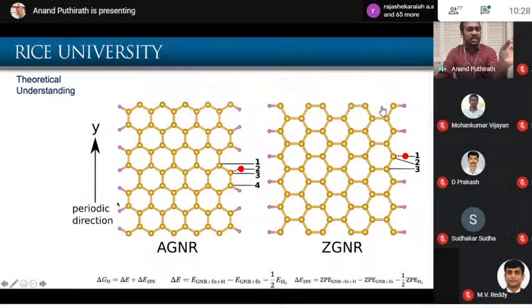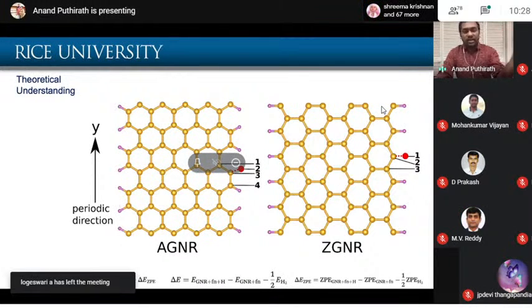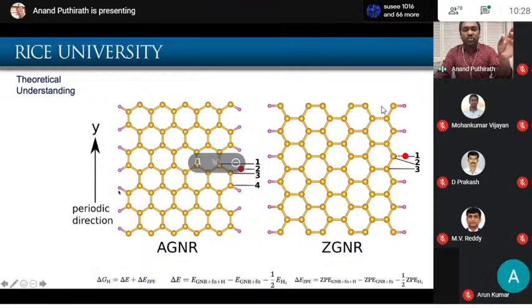In the supercapacitor case also, it is coming close to the surface. In the catalytic surface also, these hydrogen atoms are coming close to the surface. So if it comes very close and bonds strongly, probably you will get a better capacitance because your d-spacing is less and it's very close. And for catalytic activity, you don't want that much adsorption or attraction, because it should come closer to the surface and it should be able to transfer the charge, and then it should be released. If it cannot get released, that will make the whole catalytic activity slower. So these are just opposite to each other.